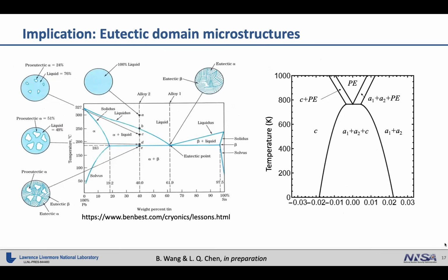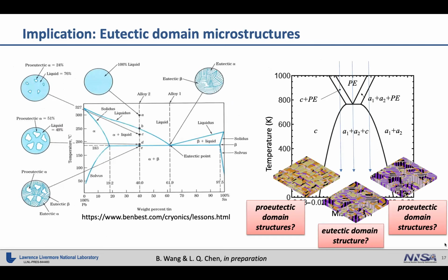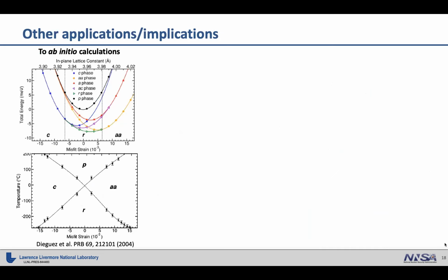I want to highlight one implication. From the chemical phase diagram, we know the microstructure in the two-phase region depends on the position of the overall composition with respect to the eutectic point. And this gives us a new understanding of the strain phase diagram. We can understand the formation of domain structure as eutectic domain structure when cooling down at the eutectic point in the strain phase diagram. Or if there's a deviation from that, it will generate proeutectic domain structures, where the microstructures are quite different from the eutectic point. And there are a few other applications or implications.